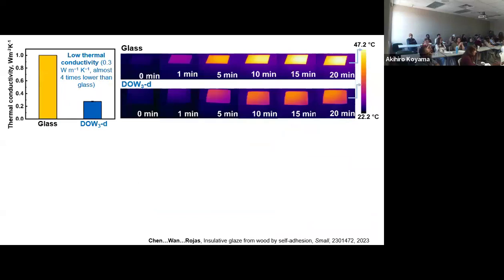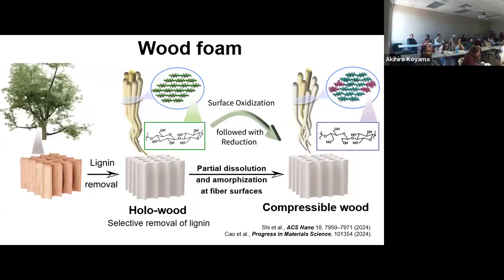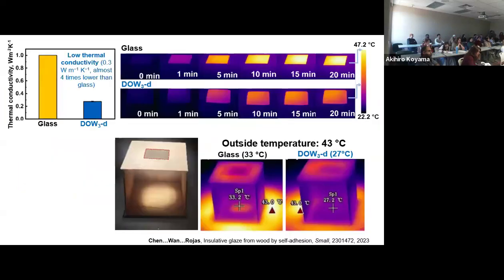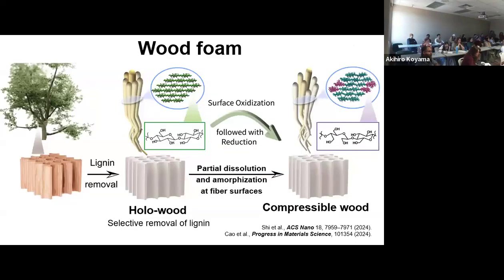And then as far as the thermal resistance, you can see here the thermal conductivity plot of glass versus this material, much less, right? So that's good, meaning that we have a glassy material that is transparent, but can also be an insulator, right? As a concept, it works very well, and we play with a bunch of things to show that.